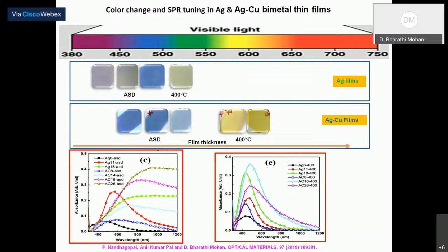Now there are three things noticed. One is the long tail has disappeared. The second one is the SPR strength is increased, and you can see the intensity of the SPR is increased. And the third one is the red shift. That means the blue one, which corresponds to the silver copper bimetal thin films annealed at 400 degrees, and the SPR maxima is appearing around 500 nanometer.